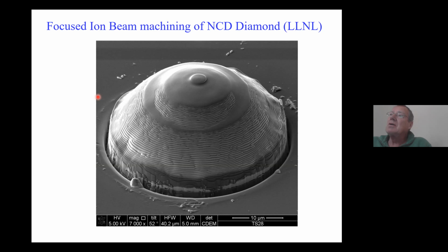Yeah, I agree. I think it's the shock equation of state, the isotherm, which is really the primary calibration. But if you have an independent measurement of the bulk modulus or acoustic velocities, and you have a measure of the volume, then it's independent. The trouble is those measurements haven't been done above, say, 0.5 megabar. That's a good point, Russ. I think the so-called absolute equation of state is still elusive in the pressures we are talking about.